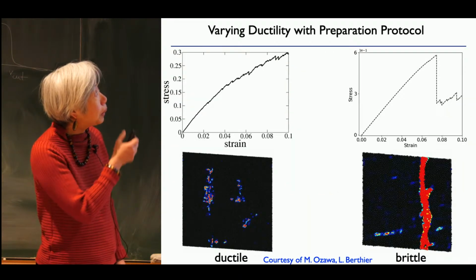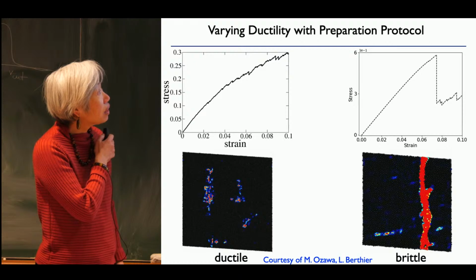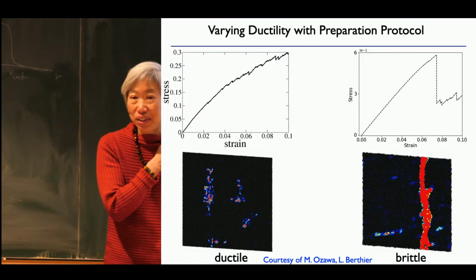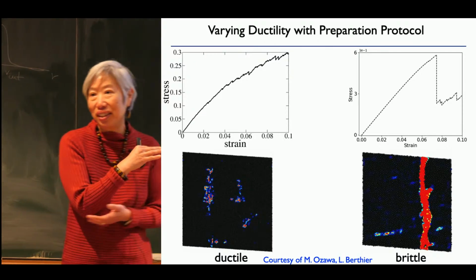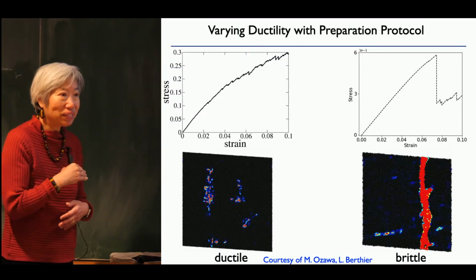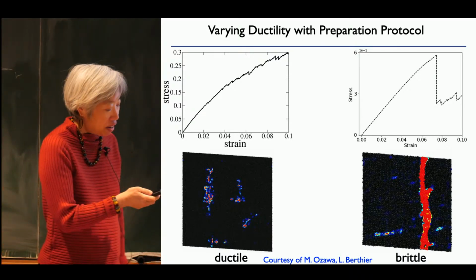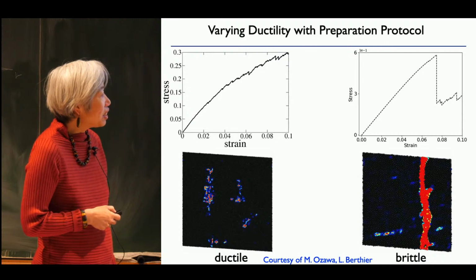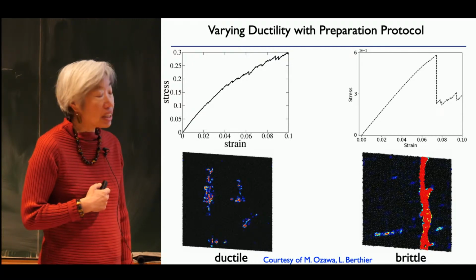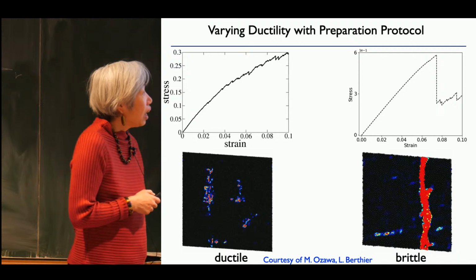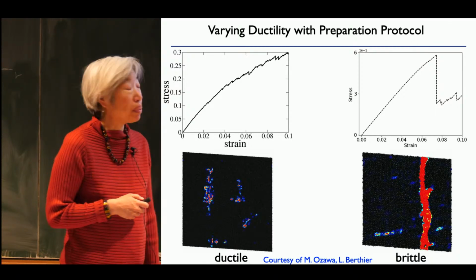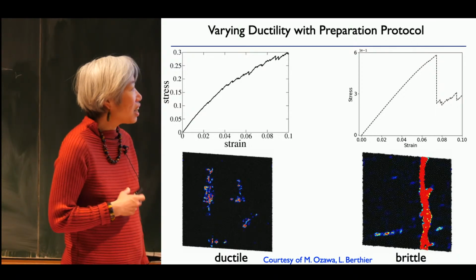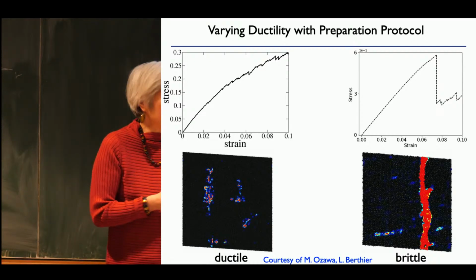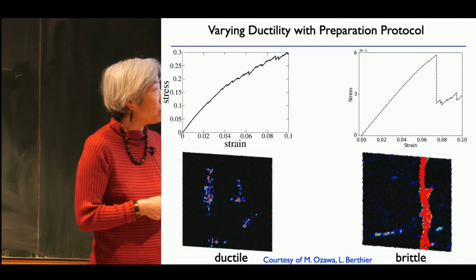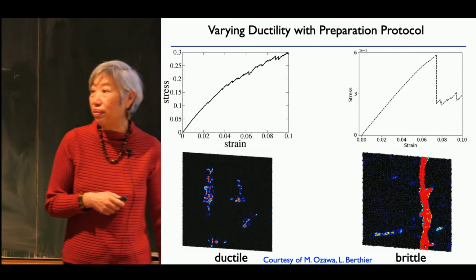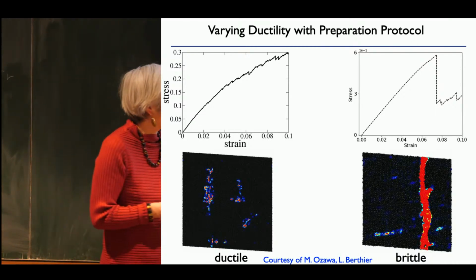All right, so here is the problem. When you take a system and you shear it infinitely slowly at 0 temperature, or very slowly at 0 temperature, these are configurations that were attained by Misaki Ozawa and Ludovic, using Monte Carlo swap. And so these are configurations that were quenched from different temperatures. So this is a system that was quenched from a high temperature, and this is a system that was quenched from a very low temperature, down to 0.